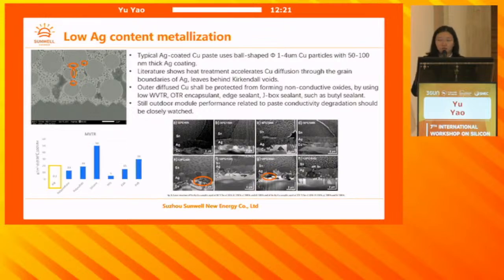Therefore, in modules you need good protection using encapsulant with low water vapor transmission rate and low oxygen transmission rate. You have to protect the module from the edges, from the J-box, for example, using this butyl sealant.